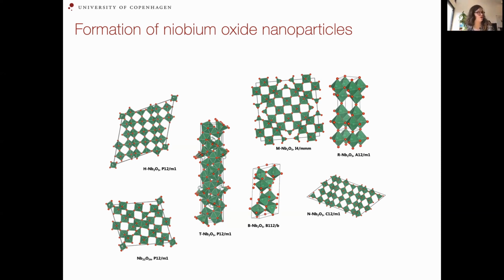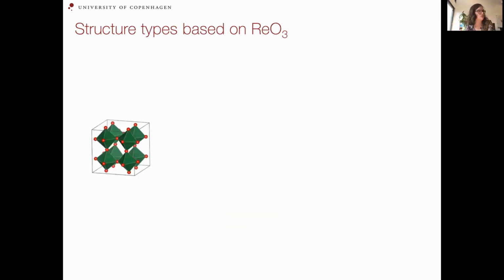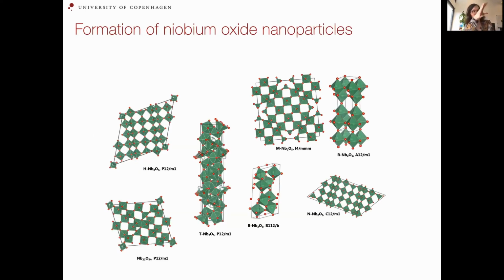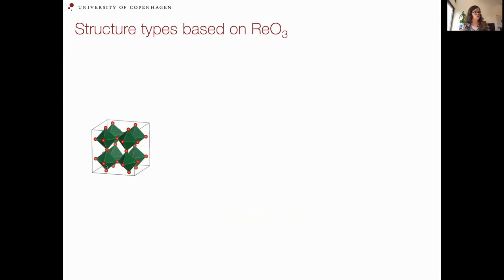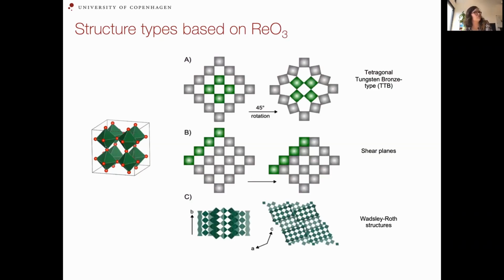For those of you that are used to looking at unit cells and materials, you see something like this really looks fairly funky and maybe not so physical. So there's a lot of work to be done in understanding the structure of these. But we wanted to see how a specific polymorph comes along. Well, we can first just see a little bit about the structure types. A lot of these materials are based on a very simple structure motif, which is this unit cell here. This is called the rhenium oxide structure, and it's just these 4 or 8 niobium oxygen polyhedra sitting together in this simple way.